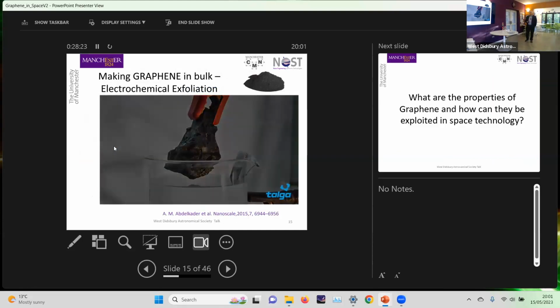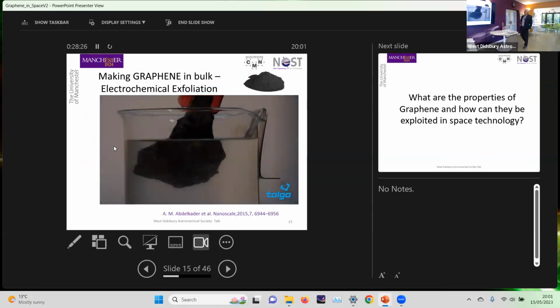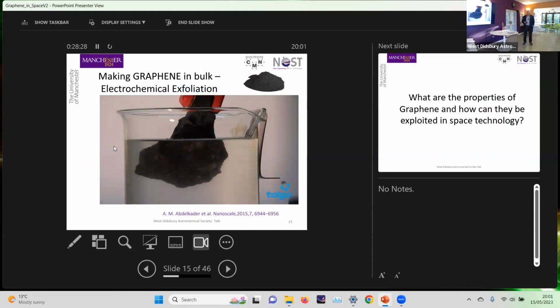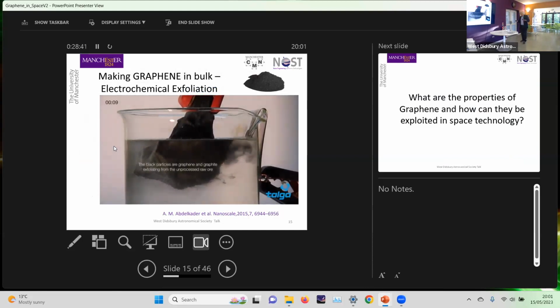Now, there is another way of making that powder. This is an electrochemical technique. We put some graphite into a beaker full of electrolyte, make a circuit, so we're driving some electric current around there, and what do we find? We find that the electrolyte ions get in between the layers and force the layers apart. And you can see that happening there.